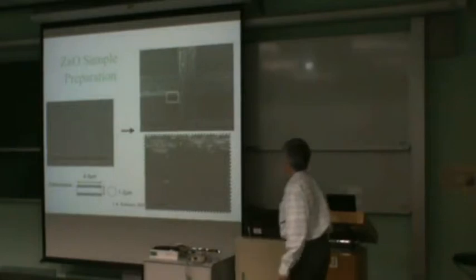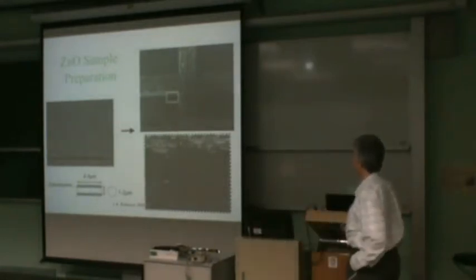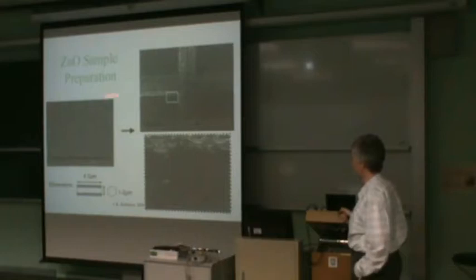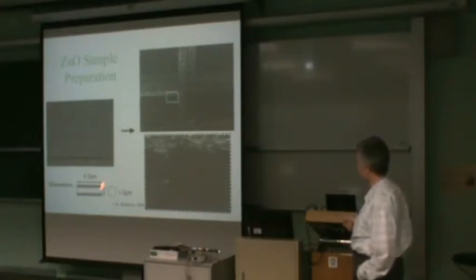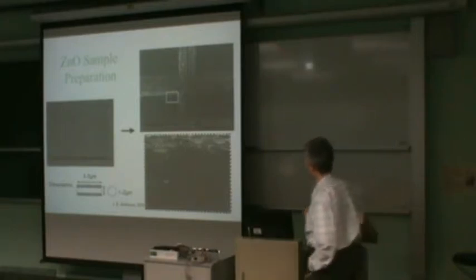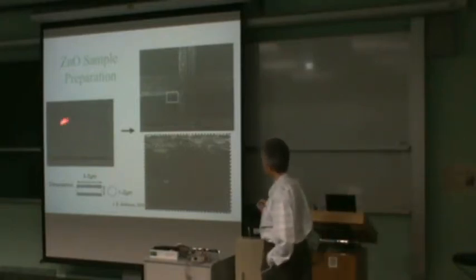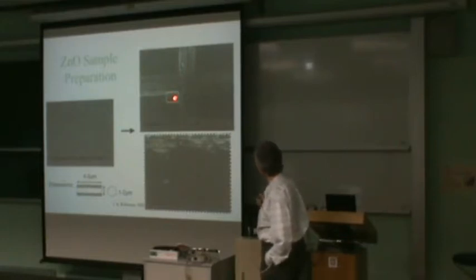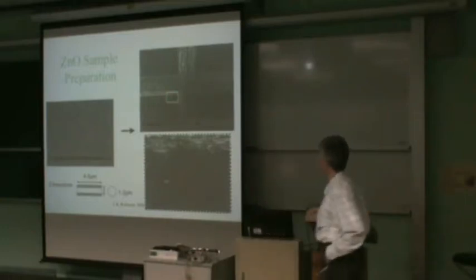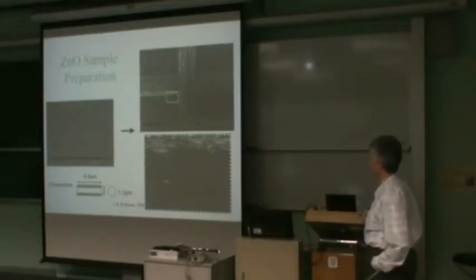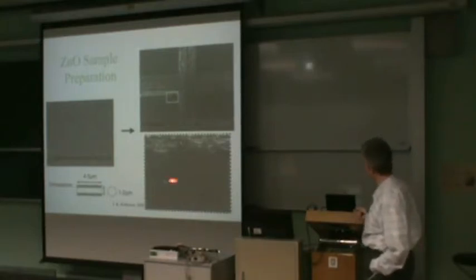Okay, a different kind of nanowire. This is zinc oxide, and here we've used a vapor transport method to grow crystals of zinc oxide. These are in the micron size range. They're just about handleable, and Marcus Newton, who did these experiments, was able to manipulate single wires onto a marked region of a silicon wafer. So if you strain your eyes, you can just see one wire at that position right next to a little scribed cross on a silicon wafer. There's a zoom of it, and you can definitely see it down here.